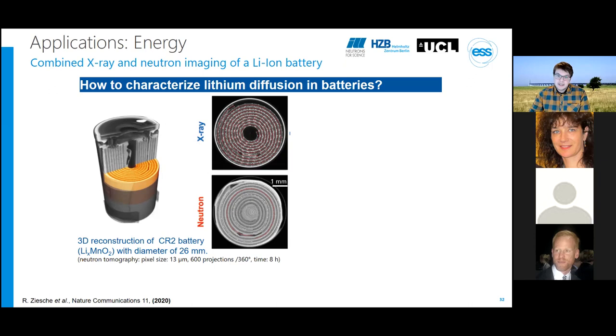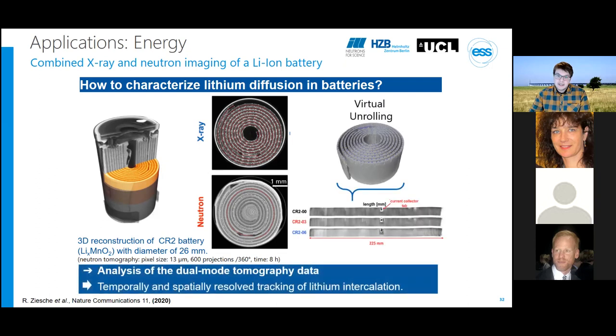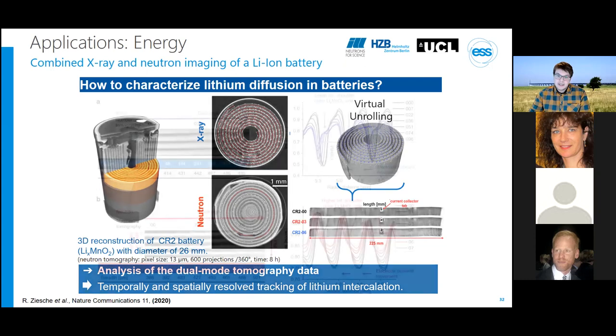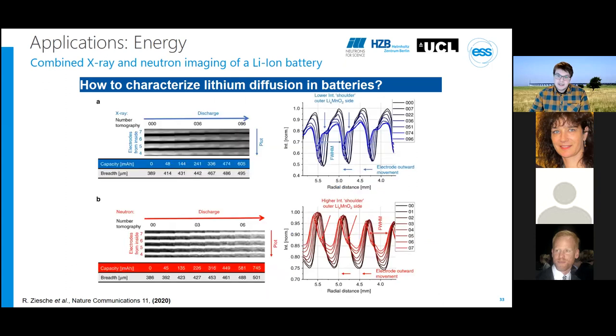The big challenge here really lies in investigating the lithium distribution and the change of the cathode anode structure inside this wound battery assembly. And to overcome this, the colleagues employed a virtual unrolling technique that allows to follow the local contrast changes more easily, and in particular to follow now the lithium intercalation at different stages. And here you can see three different discharging states. And if you take a segment of the battery and unroll it, then you can see here what happens with the electrodes, both with X-rays seen on top here and with neutrons seen on the bottom.